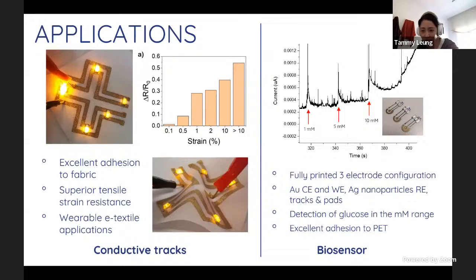we were able to make different types of applications, such as conductive tracks and a glucose biosensor. The gold conductive tracks are printed onto a polyester substrate, which showed excellent tensile and compressive strains. Again, there was excellent adhesion during testing, where we never saw delamination of the film from the surface, as it continued to be conductive beyond 10% strain. This has important implications in the wearable electronics industries, as electronic textiles themselves must be able to withstand at least 10% strain.